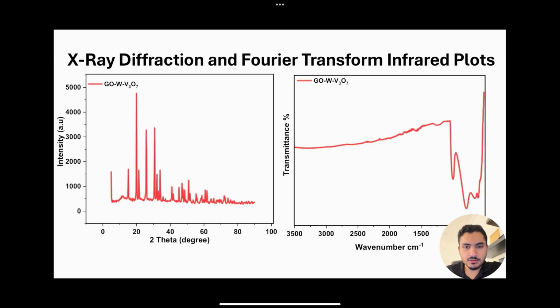Then we have the XRD and FTIR. On the left we have the XRD plot, where we have the most intense peak at around 21 to 22 degrees, indicating successful binding of graphene oxide and tungstate in the V₂O₇. Additionally, we have several sharp peaks indicating the crystallinity of the material.